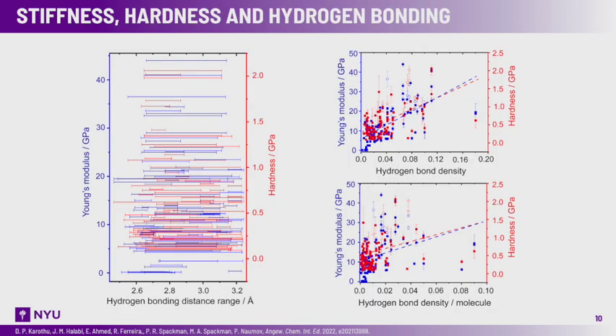And this plot here on the left shows that there is no correlation with the intermolecular hydrogen bond distances. But if you compare the hydrogen bond density, which is basically the number of hydrogen bonds per volume of the unit cell, then there is some kind of small, or weak, correlation, I would say. And the same goes for the hydrogen bond density per molecule, where we have the same property but divided by the number of molecules. And so these are, I would say, the first insights of how we can actually design very hard organic crystals, and those will be the best candidates for applications.